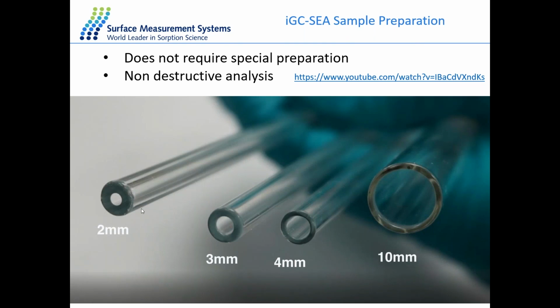We also offer different sizes of columns. We have 2 mm, 3, 4, and 10 mm columns. 2 mm columns are for fine particles. 3 mm columns are for slightly larger particles. 4 mm columns are to accommodate fibrous materials and larger samples. The 10 mm column is specifically for samples that you don't wish to break up. So this could be a block of wood or a tablet sample where you want to analyze the sample whole. In this case, with a 10 mm column, you would need a slightly larger column oven to accommodate.